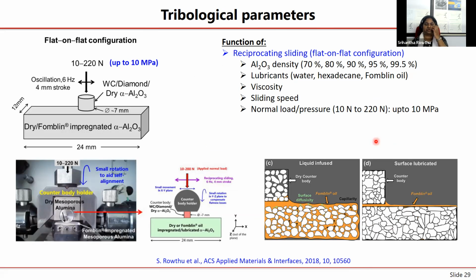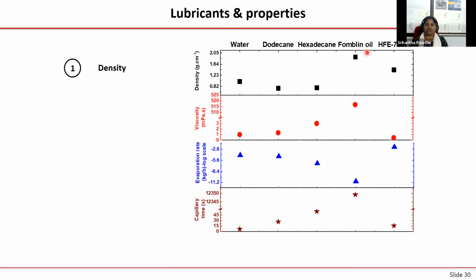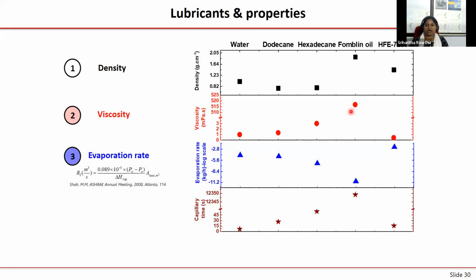Yes, so before this particular conclusion, I already said that among the three liquids, Fomblin oil was the best lubricant. There are some reasons I wanted to show you why it is. If you look at the density of all the lubricants, there are like 5 liquids I initially began with. Fomblin oil has higher density. Then if you look at viscosity, it has higher viscosity, and evaporation rate is smaller. So you want the viscosity of your oil to be higher, right? Then only the solid contacts between your counter body and the bottom specimen are going to be minimized. Remember your Stribeck curve. It's better to have high viscosity oil.